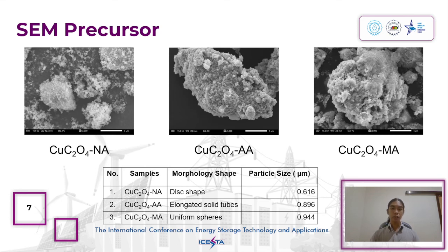SEM, or scanning electron microscopy analysis, was used to evaluate the particle surface morphology, structure, and diameter size at a random point. The testing process required collecting images at a magnification of 5,000 times. The first figure shows the SEM of the nitric acid sample, obtained from the precipitation reaction, demonstrating a disc shape. The second figure is the sample of acetic acid that demonstrates an elongated solid tube. And the third figure shows the malic acid sample featuring uniform spheres.